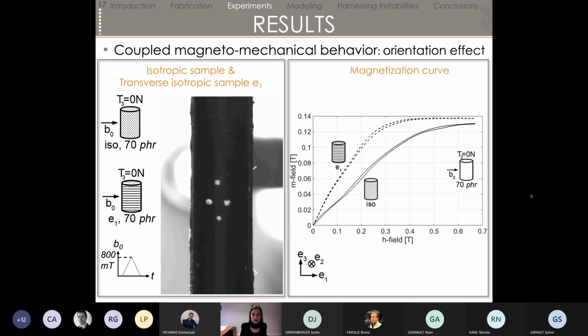Last point about our test is the magnetization curve. What we see here is that the sample for which the chains are aligned along the direction of the magnetic field magnetizes very fast, so the slope is really high, and it stabilizes pretty fast and steadily, so we have a saturation that's clearly marked. For the isotropic sample, magnetization is much slower, and that is due to the fact that your particles need to move to realign slowly with the magnetic field. So they need time to attain their optimal configuration.